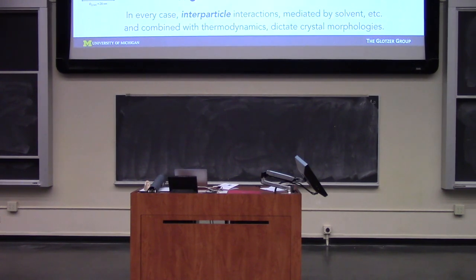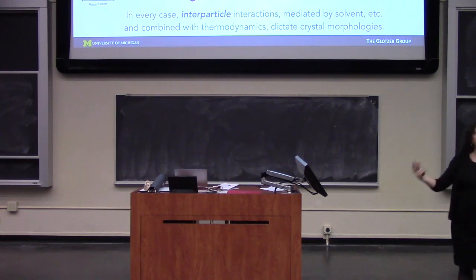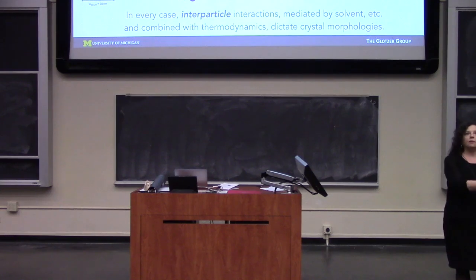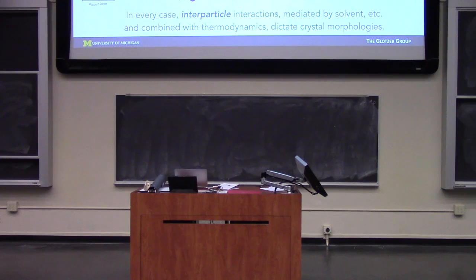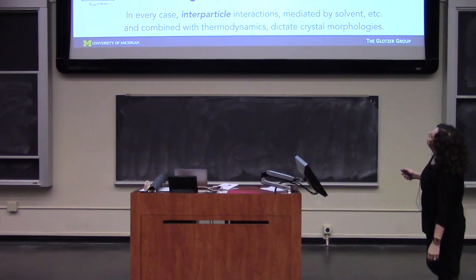And so this class of soft matter building blocks can also self-assemble into crystal structures of extraordinary complexity, many of which are isostructural to atomic crystals, meaning there's an atomic crystal where the atoms are exactly where the big particles are. Of course, the lattice spacing is much bigger for the nanoparticles, but they sit on the same lattice sites. Here are some examples from various groups. This is an example, I think, from Dmitri Talapin's group at Chicago, where they have a binary mixture of different size spheres that self-assemble into these very interesting and complex lattices.